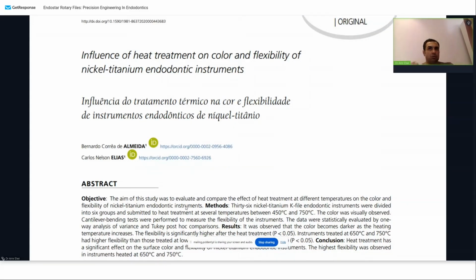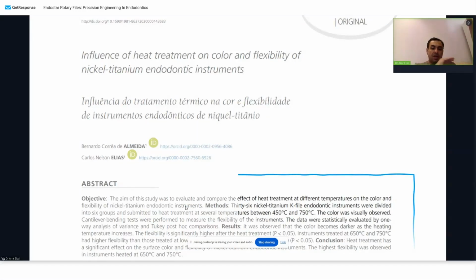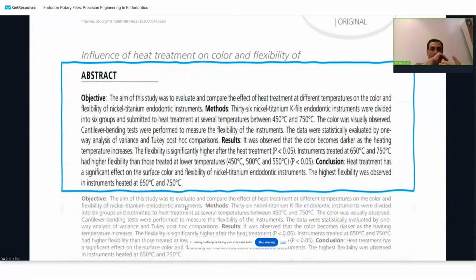Do you remember when I told you I don't like that I have a file which has 2 to 3 colors? This study was done on 36 NiTi files. They did the heat treatment from 450 till 750. They found a color change. What they found is that the color change impacted the flexibility and the ability of the file or the wire to take higher curvature, which for us means to take higher canal complexity. So they found that the temperature will impact the color and flexibility, with higher flexibility for higher temperature.